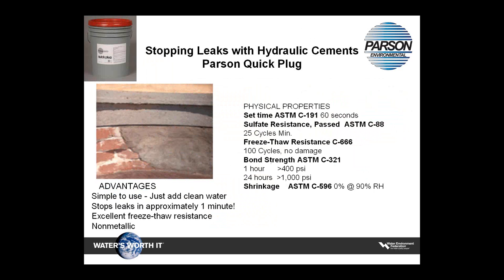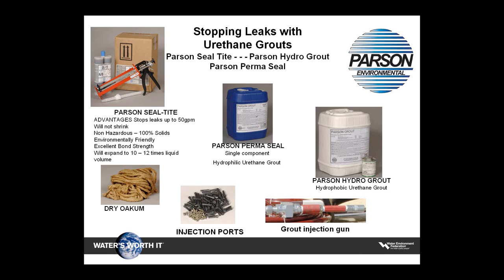Stopping infiltration is a necessary but fairly easy step in tightening up your manholes. Parson Quick Plug is an easy-to-use, fast-set hydraulic cement with a set time of 1 minute that is capable of stopping small to medium-sized leaks. For higher volume leaks, we recommend urethane grouts. Parson Seal-Tite is a hydrophobic urethane that is dispensed from a dual caulk gun. It has an initial reaction time of about 5 seconds and can stop active leaks up to 50 gallons per minute. Parson Hydro Grout and Permaseal are injected through the manhole wall using injection ports and pumping equipment.